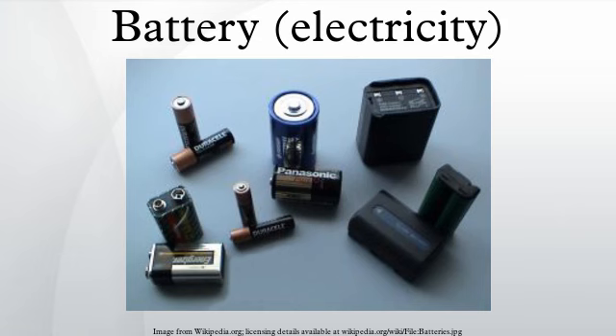Corrosion: internal parts may corrode and fail, or the active materials may be slowly converted to inactive forms. Physical component changes: the active material on the battery plates changes chemical composition on each charge and discharge cycle. Active material may be lost due to physical changes of volume, further limiting the number of times the battery can be recharged. Most nickel-based batteries are partially discharged when purchased, and must be charged before first use.